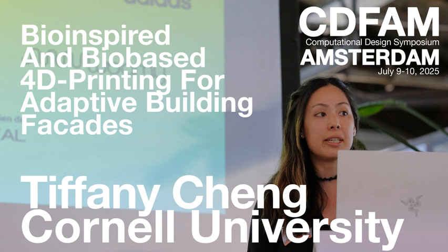By programming the extrusion path with a 3D printer with different parameters, such as spacing and layer height between the paths, you can control bending in different directions. You can control the amount of bending, and you can also control the speed of bending. And by combining and stacking together these different bilayer building blocks, as I call them, you can expand the geometric possibilities. So this extrusion process is kind of like an analog material code that tells the material what shape it should transform into.